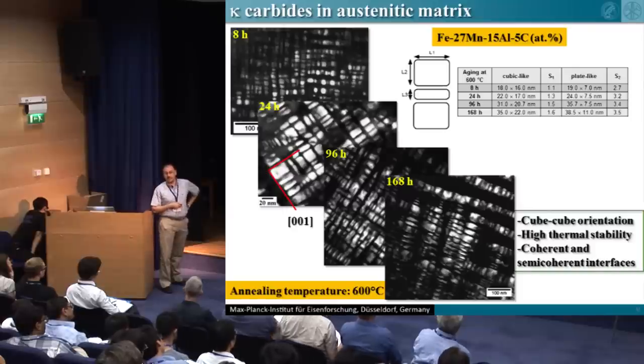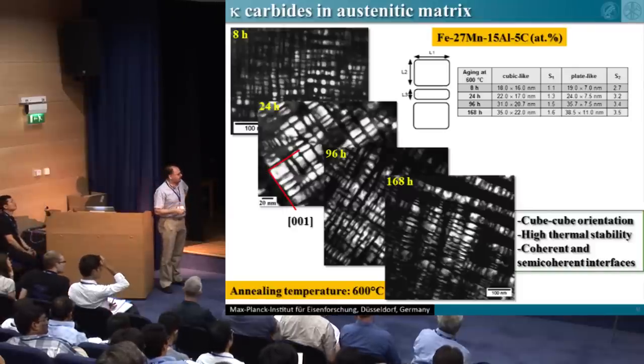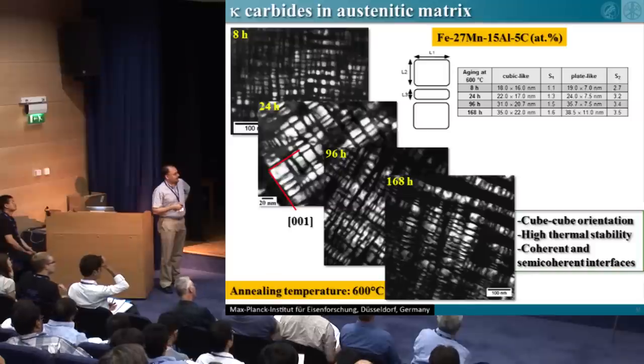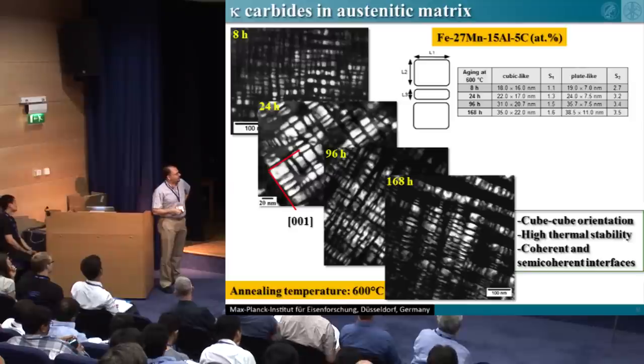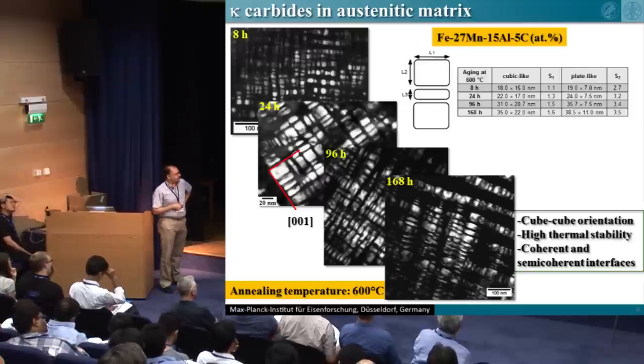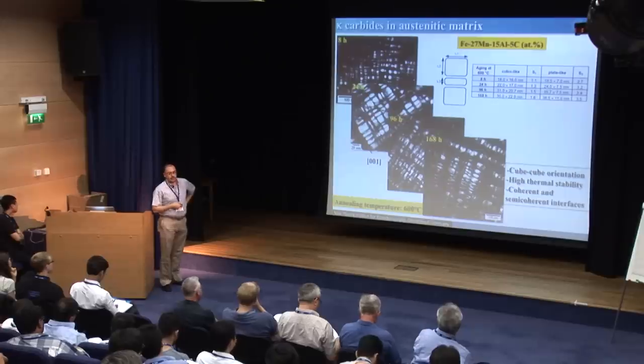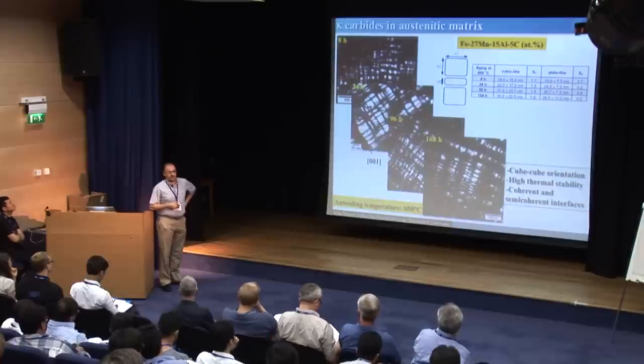So it's similar to what we have in gamma prime superalloys. And it's also interesting, the high thermal stability of these phases in terms of size. Up to 2 weeks at 600 degrees, we are still below 50 nanometers in size. And also the high level of coherency of the interfaces. Of course, it depends on the time, but basically we have coherent and semi-coherent interfaces, and this has a huge role on the mechanical properties.